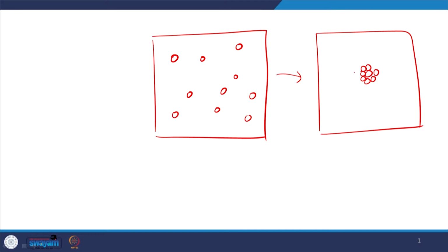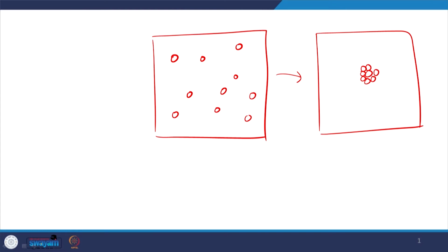And now, instead of looking at the Rg of a single molecule, we can look at the Rg of the entire system. And in this case, we naturally will find that Rg is going to be large because the molecules will occupy the entire volume. You can see that by defining a center of mass, and clearly the positions of the molecules, the Ri, are farther from the center of mass in the left case compared to the right case.